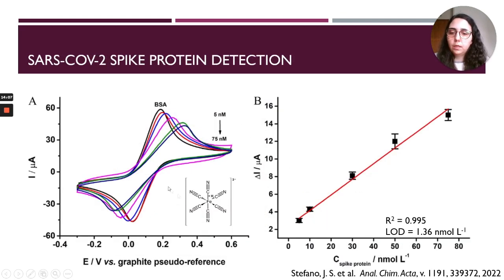Here you can see some voltammograms in the absence of S protein, shown here in black, written in BSA, and some voltammograms showing the difference in the signal after different concentrations of S protein are added. We can see that the peaks here from, again, ferrocyanide, decrease with the increase of S protein due to the blocking of the surface. If we plot the delta of the current versus the concentration of spike protein, again, we do get a nice linear curve with an LOD of a few nanomolar, which is quite good.